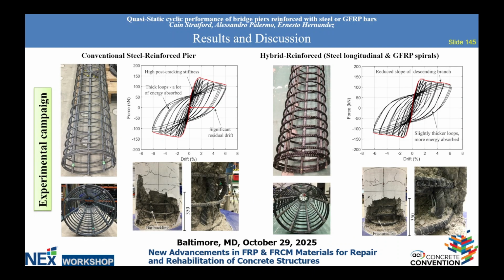Obviously there has been a lot of other work done, especially by the Canadians, but this was detailing with the New Zealand standards. And I believe this is actually one of the largest tests. We went almost to 2 feet in diameter. As you can see here, if we compare the conventional with the GFRP spiral, you have the benefit. You can see that the post-peak is slightly better, and you have slightly larger loops. The reason is, if we also look at the damage, the plastic hinging is 350 millimeters, so 14 inches. And the same here.